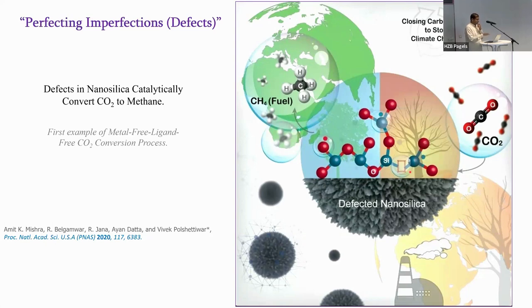So I'm not going into the details, but that's what we showed here in this work, that yes, you can generate these defects systematically, and we showed that the cooperativity between the radical defect and the oxygen vacancy together activate the CO2, dissociate the hydrogen, and convert CO2 into methane, right? Without any metal and without any fancy reaction, which is a purely metal-free, ligand-free reaction. Only drawback was activity. If I compare the production rate of this process with the metal, then this is 10 times less than the metal. So obviously, it's not sustainable.